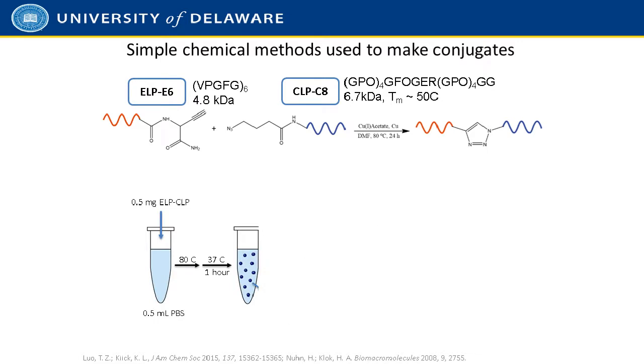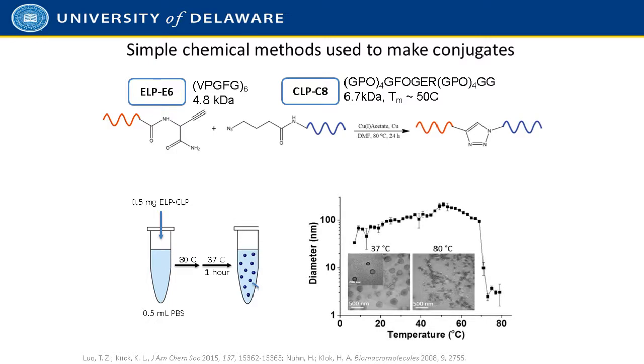these conjugates that have the thermo-responsive ELP shown in red and a collagen domain that can fold into a triple helix shown in blue. We simply put these peptides in solution, heat them up to unfold the collagen-like domains, and then incubate them at 37 degrees to form particles. And then this is dynamic light scattering data showing the particles have diameters on the order of 100 nanometers. They are temperature responsive. They get larger at higher temperatures, and then the particles dissolve at higher temperatures. The diameters are useful for drug delivery.